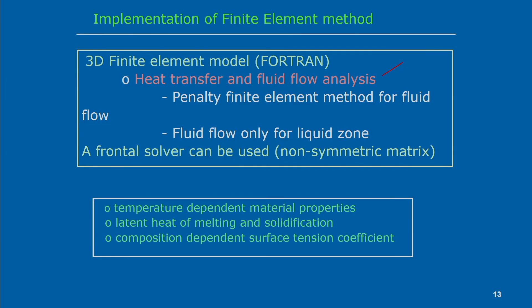A frontal solver can be used to solve the linearized equations, assuming a non-symmetric matrix with velocity field in particular directions. Temperature-dependent material properties are important for correctly defining material behavior; latent heat of melting and solidification is considered to predict phase change from liquid to solid. Finally, composition-dependent surface tension coefficients must also be modeled for the fluid flow analysis.